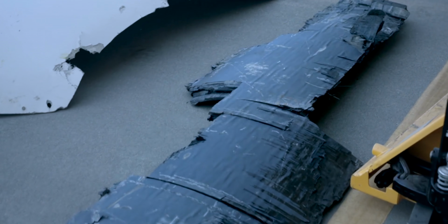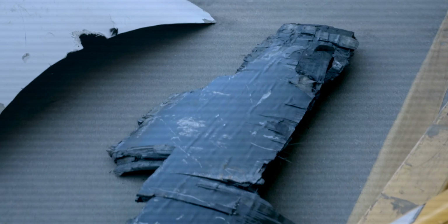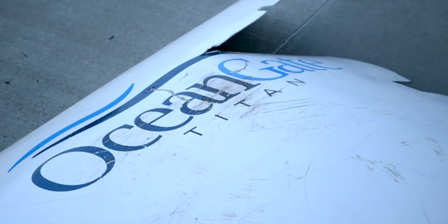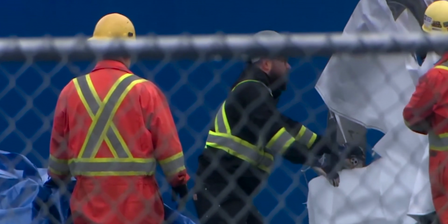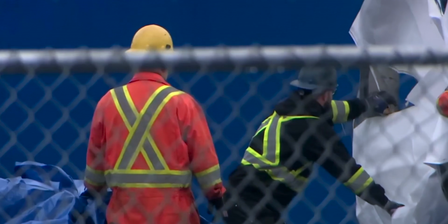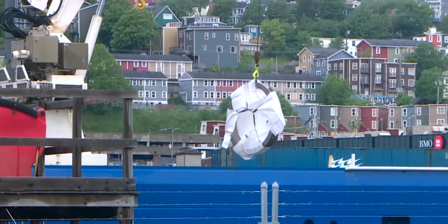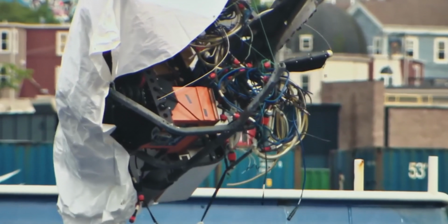Titan's actual hull told a very different story. Based on the weakest material samples recovered from the wreck, investigators estimated that those same 24 dives may have consumed more than 80% of its predicted fatigue life. Instead of barely aging, the hull had already used up most of its expected lifespan.